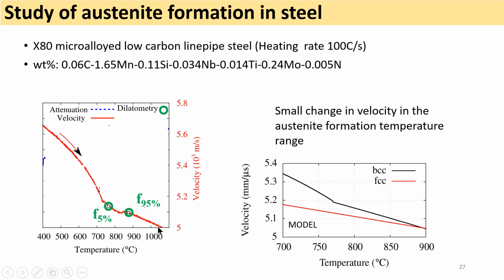What I want to show in this slide is that this is not very obvious in a velocity plot to look at the austenite formation, and I illustrate the reason why in this plot. If we look at the speed of sound for BCC ferrite in black and the speed of sound for austenite FCC, we see that in the range of temperature where the austenite formation occurs, those two velocities are very similar. It is therefore often considered a challenge to measure the austenite formation using this parameter.